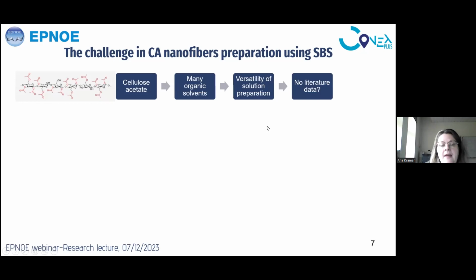And we faced many challenges in the beginning when we started working with this. Remember, I started my project in 2021. And in the beginning, we thought that it would be quite straightforward process, since we all know that cellulose acetate has substituted hydroxyl groups. And this substitution of hydroxyl groups enables cellulose acetate to be soluble in many organic solvents, if we talk about cellulose diacetate. So we have a quite wide range of possibilities to study various solvents to prepare solution of cellulose acetate to be processed by solution blow spinning.